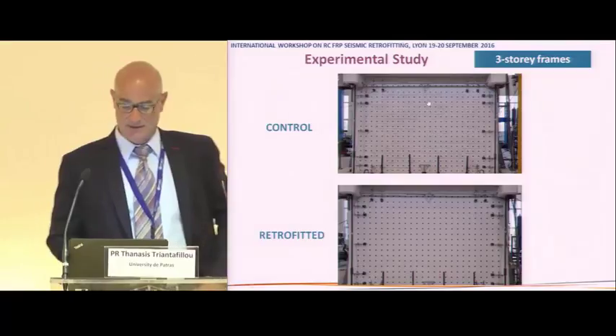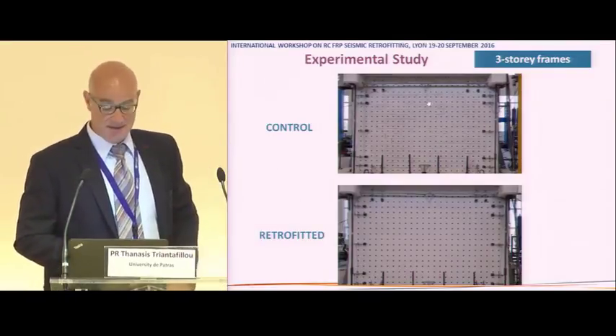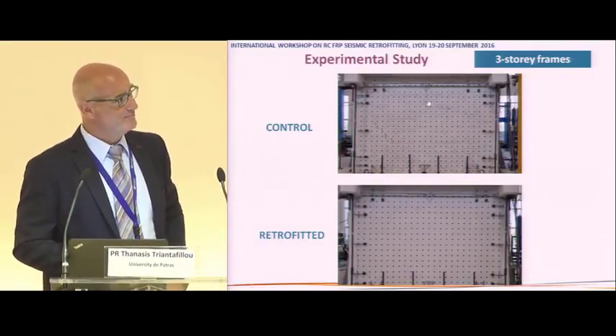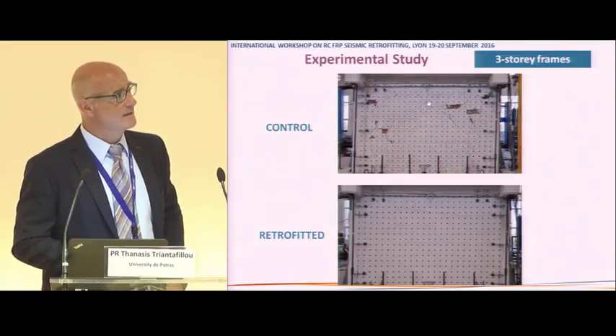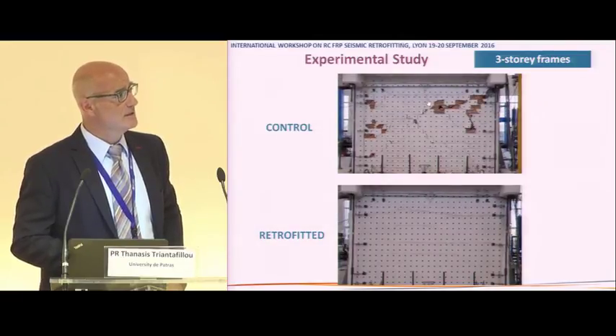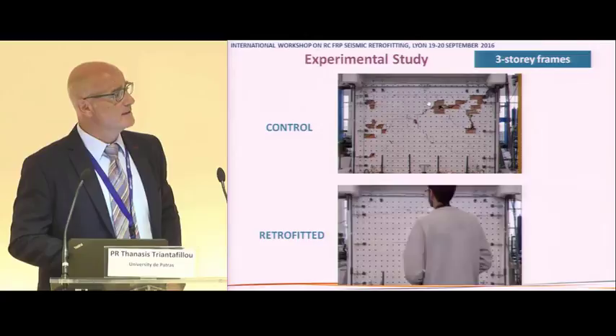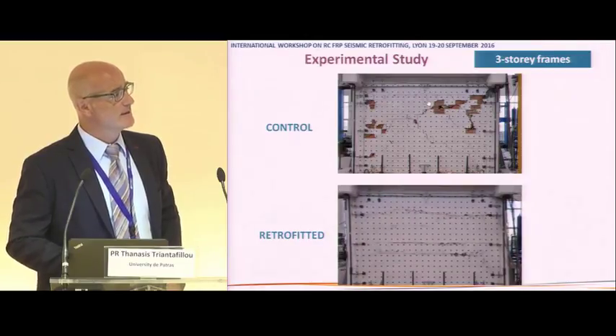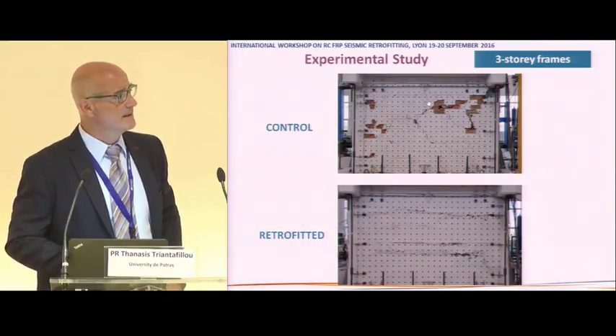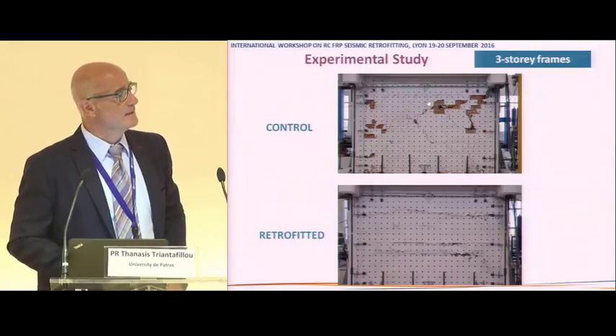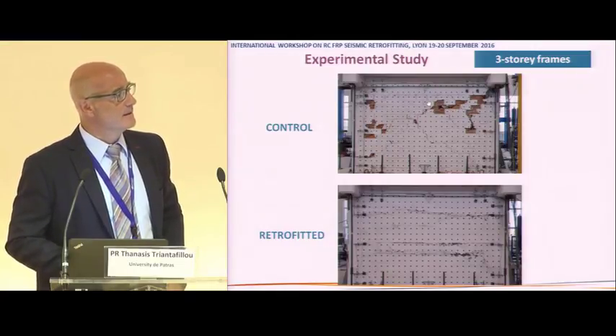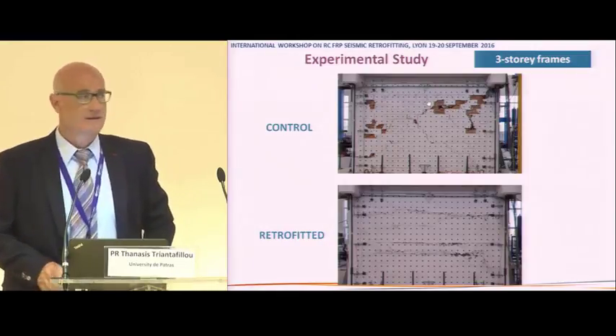I think there is a video here illustrating the difference in the damage. You see how much damage you get in the infill if there is no jacketing with the TRM system, and how this damage is limited. There is very, very little cracking in the matrix in the case of the retrofitted infill.